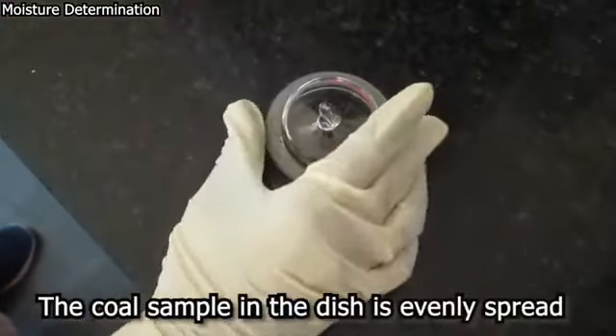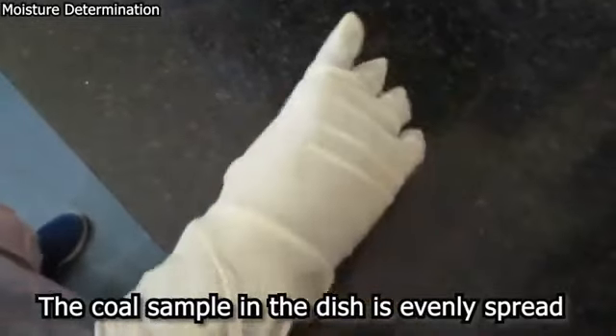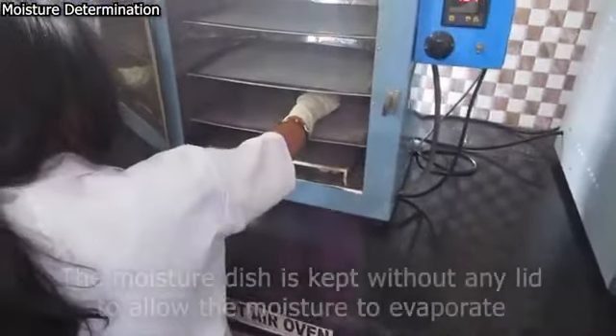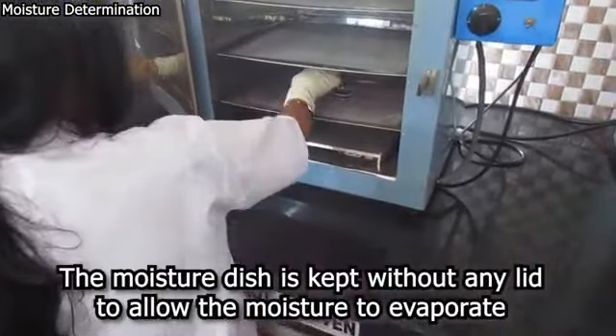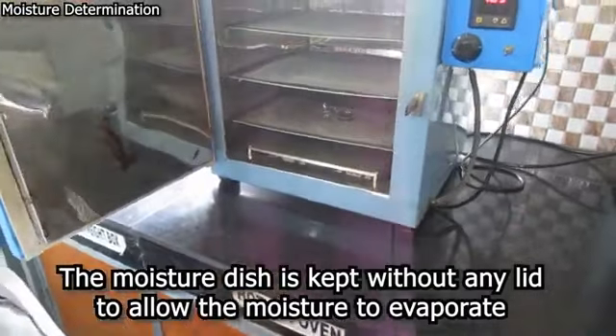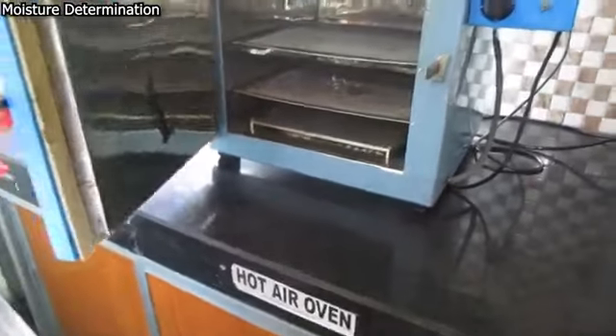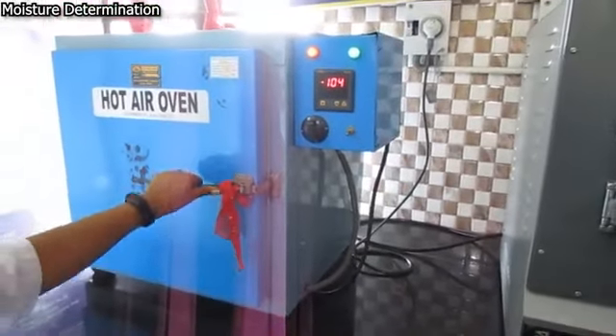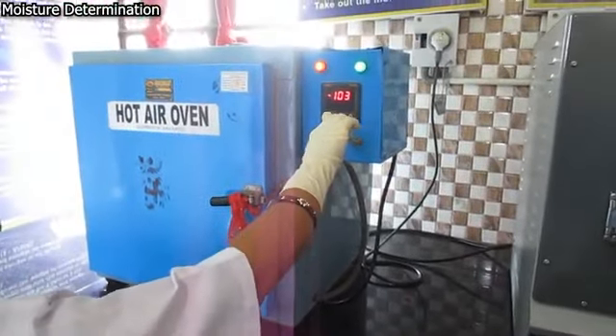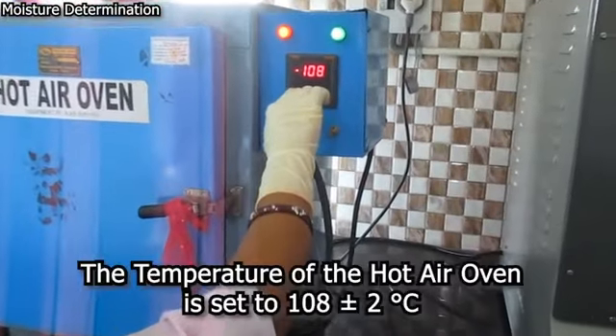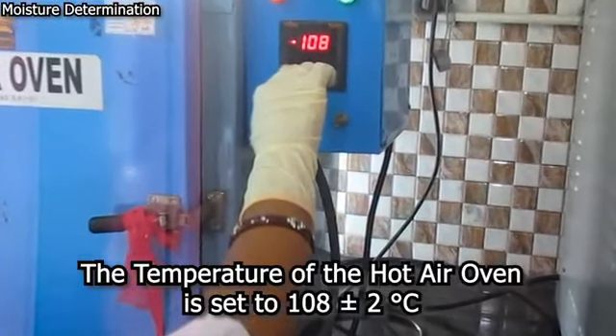The sample is evenly spread to prevent formation of lumps. The silica or glass crucible is then put in a hot air oven at a temperature of 108 plus or minus 2 degrees Celsius for 1.5 hours.